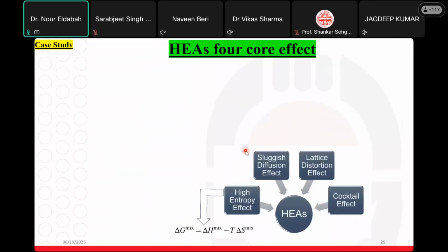What are the most important effects, the hallmark of this type of alloy, is the high entropy effect. When we look at the free energy of mixing for the alloy, we find a very high value of the term TΔS, and consequently a lowering of ΔG, the free energy of the solid solution. So a stable solid solution will be formed in this type of high entropy alloy.